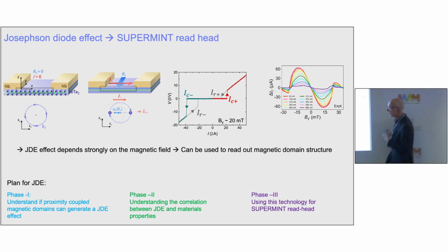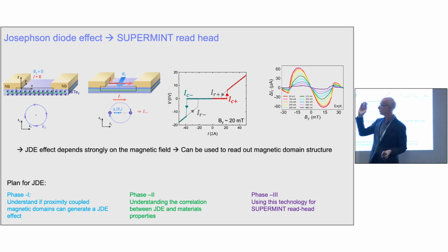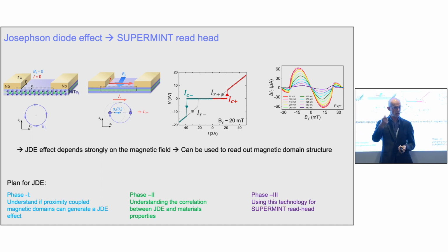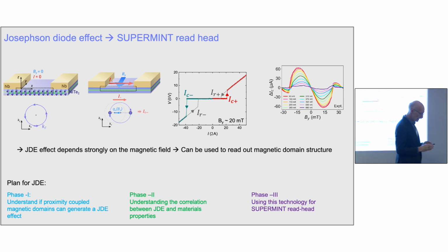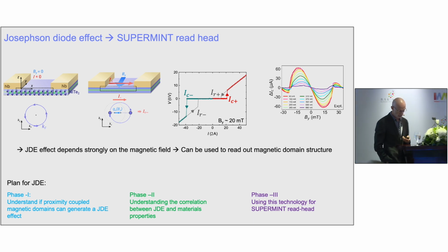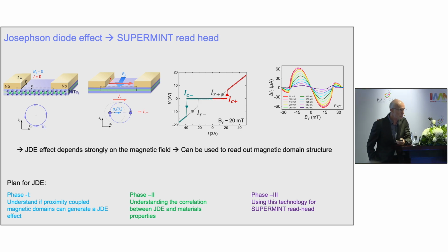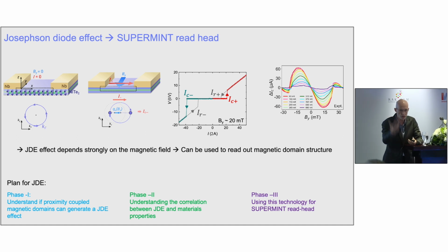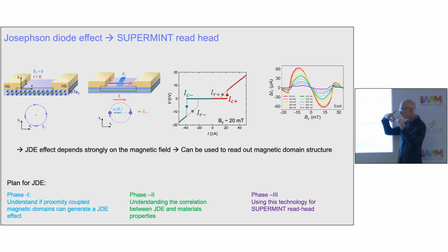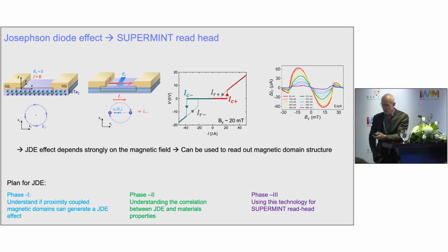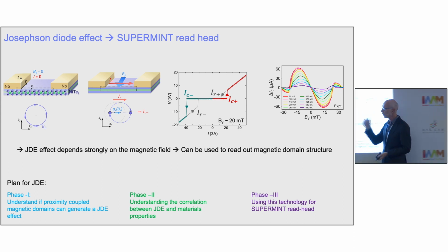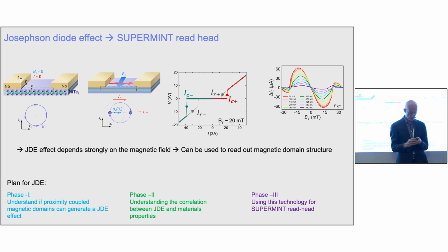In our case, we believe we've broken the symmetry through spin-polarized surface states, which are known to exist in nickel ditelluride, in which we, with Nils Schröter, who's a group leader in my institute, have demonstrated that we see spin-polarized surface states at the surface. So this should be a property common to nearly all Dirac semimetals, Weyl semimetals, topological systems. So we think this will open a floodgate to new systems. And indeed, already in the literature in the last few months, a number of papers, and we ourselves have even more interesting systems where we now see this non-reciprocal current flow.